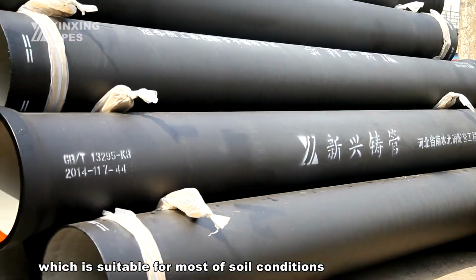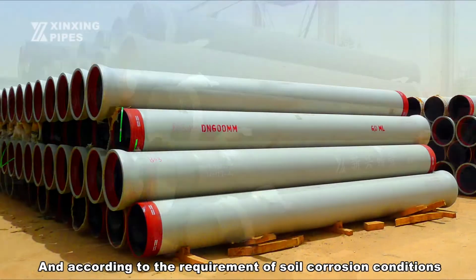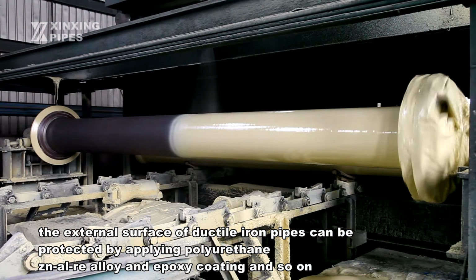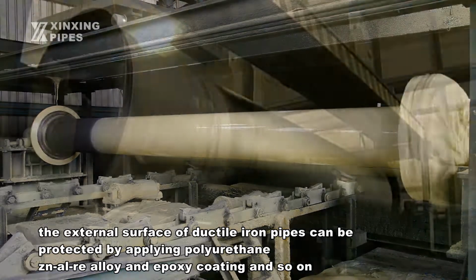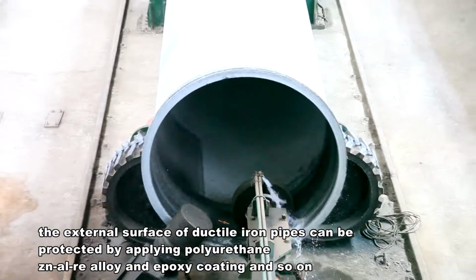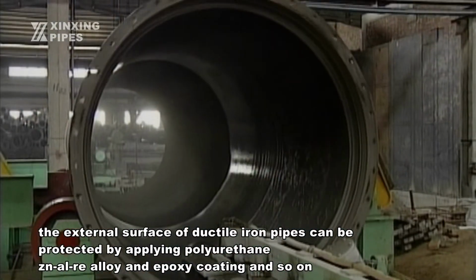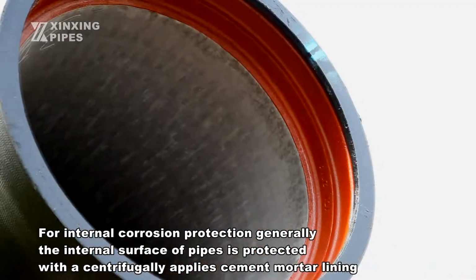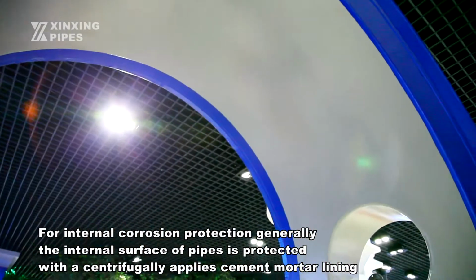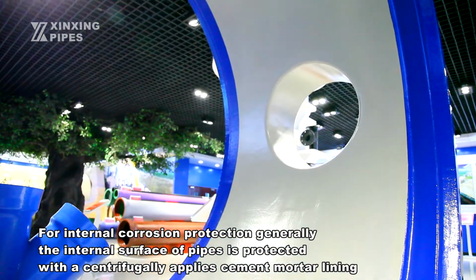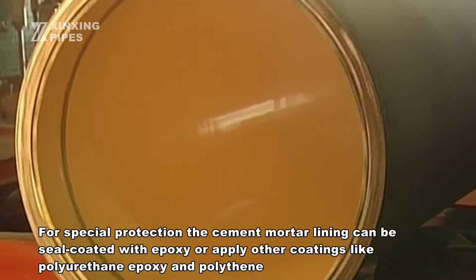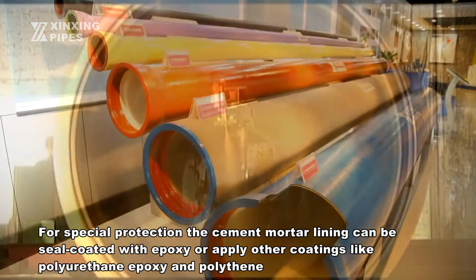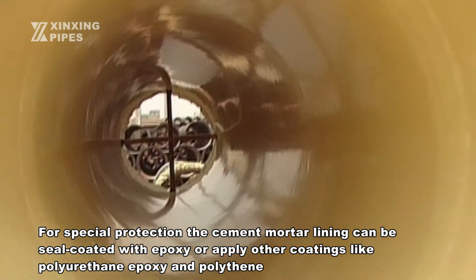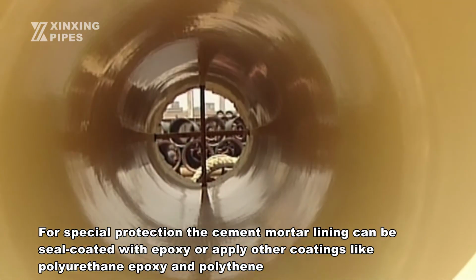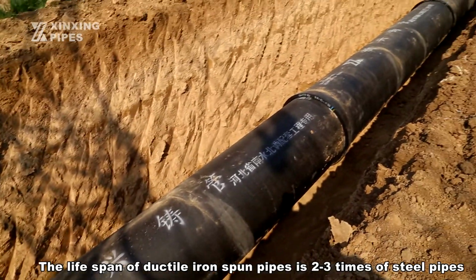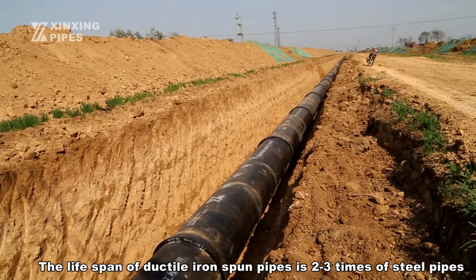most soil conditions. And according to the requirements of soil corrosion conditions, the external surface of ductile iron pipes can be protected by applying polyurethane, ZnAlRe alloy, and epoxy coating, and so on. For internal corrosion protection, generally, the internal surface of pipes is protected with a centrifugally applied cement mortar lining. For special protection, the cement mortar lining can be seal-coated with epoxy, or other coatings like polyurethane, epoxy, and polythene can be applied. The lifespan of ductile iron spun pipes is 2 to 3 times that of steel pipes.